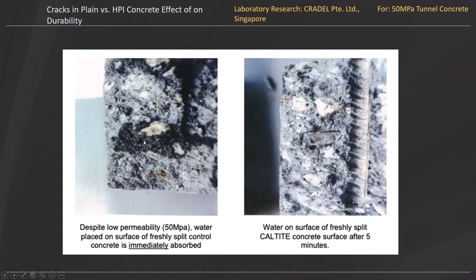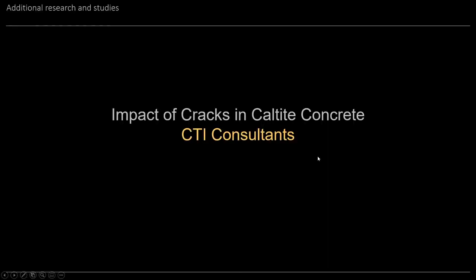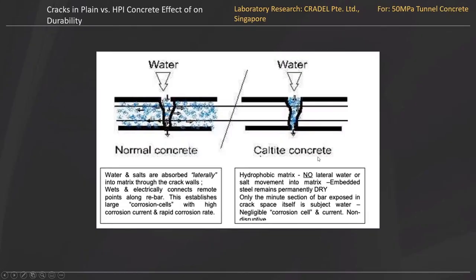You can see when the sample is broken open, you put a little droplet of water on it here, it's immediately sucked in, whereas with the one with the HPI, the water is just beading and sitting up there. Simple explanation: if water gets into a crack in concrete containing HPI, the water is retained in that crack. It does not radiate through the matrix. It does not link the anode to the cathode. In normal concrete, water goes into the crack very rapidly and runs along the reinforcement.